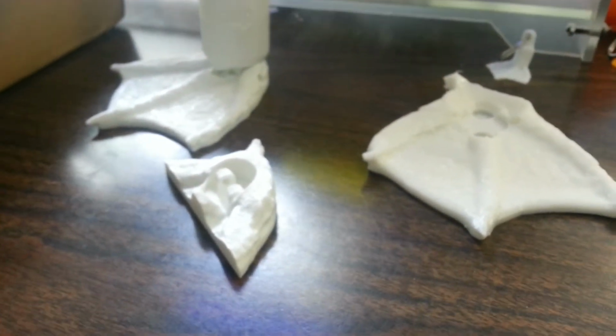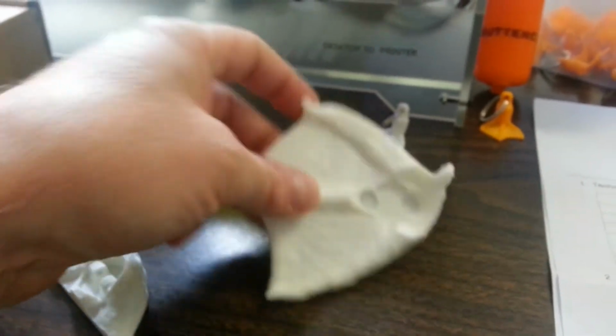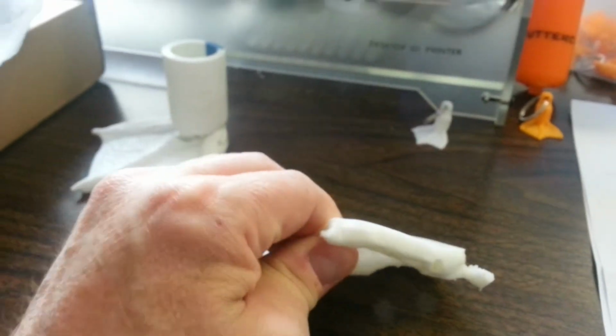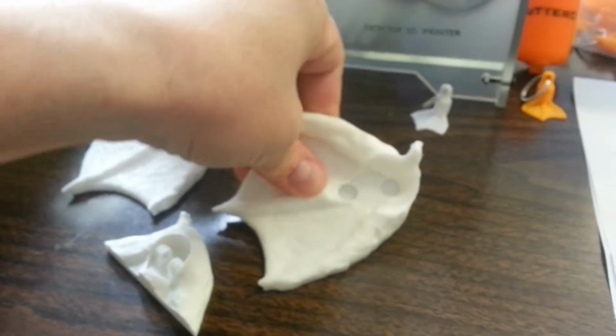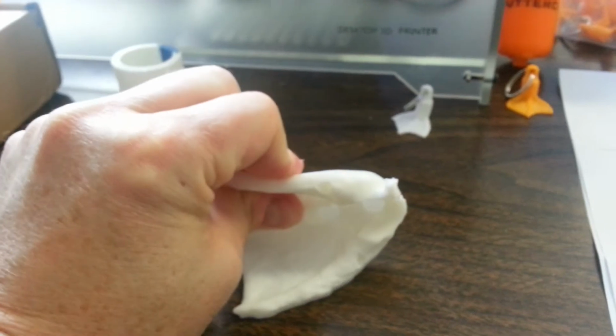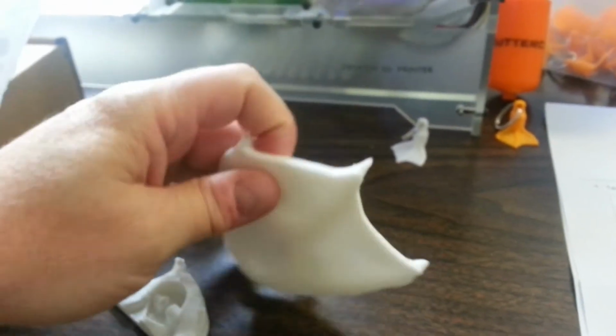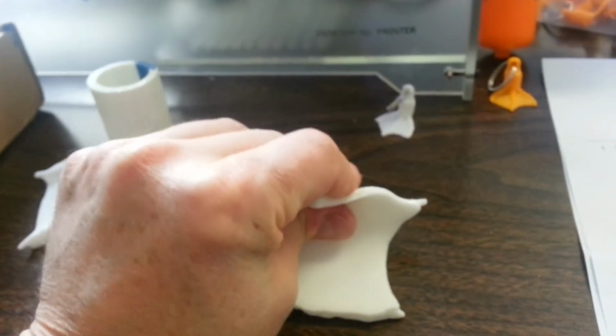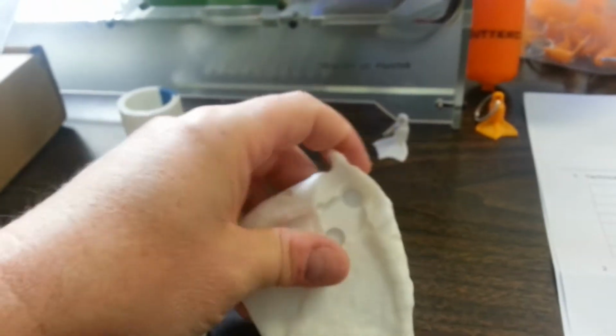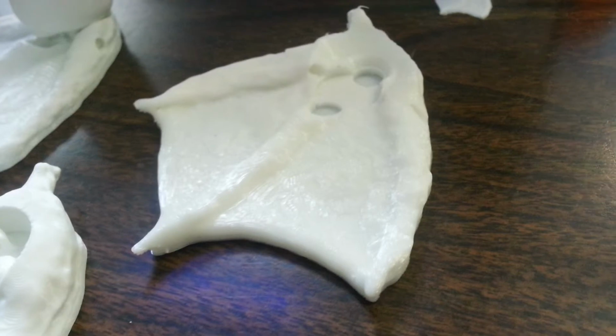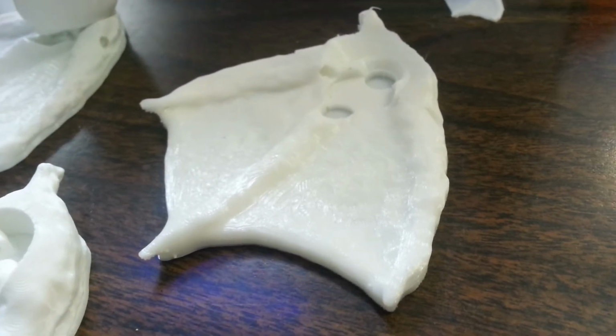I generally print at about 210 for the PolyMax and about 215 for the PolyFlex. Now, this is a bottom of the PolyFlex, and if you look at it, you'll see that I can bend it. You can bend it all the way over, and you can't break the stuff. It's got really good flexibility. It feeds really well. It feeds just as good as the regular PolyMax.